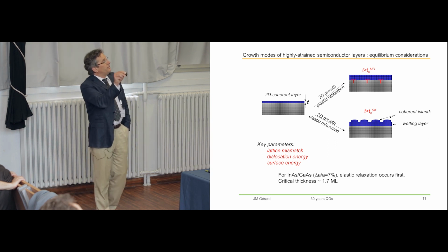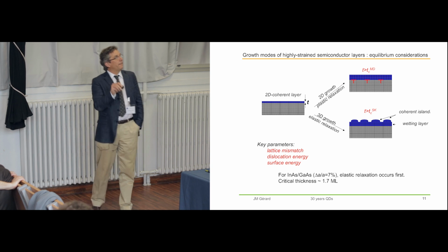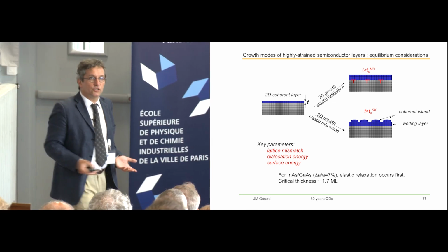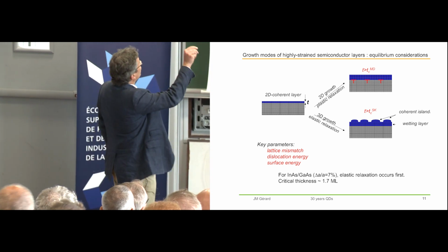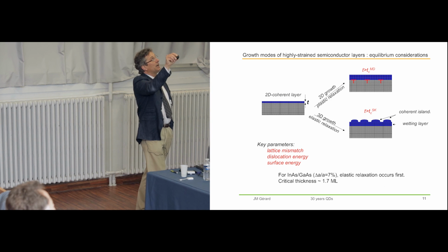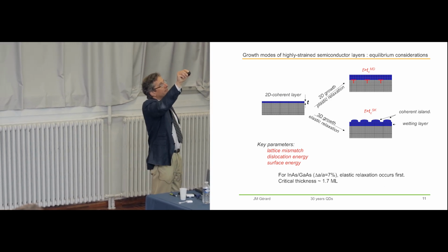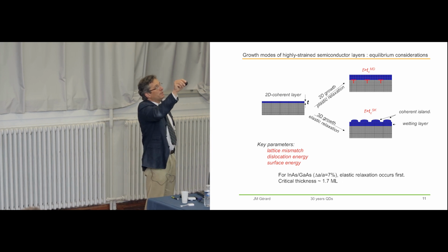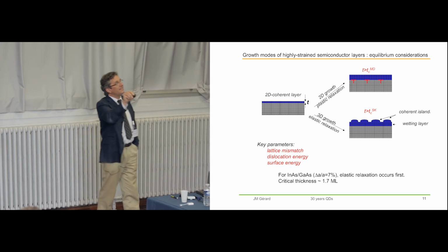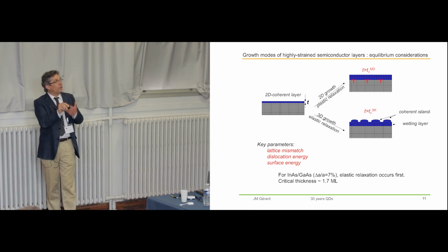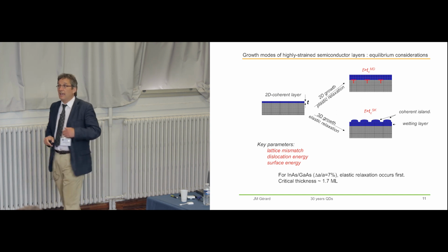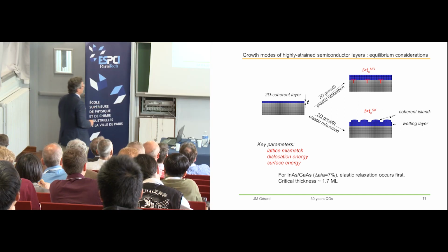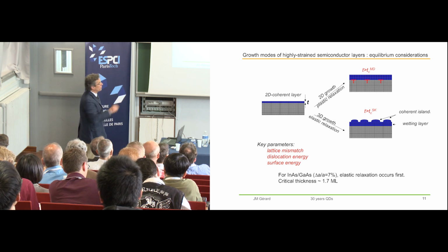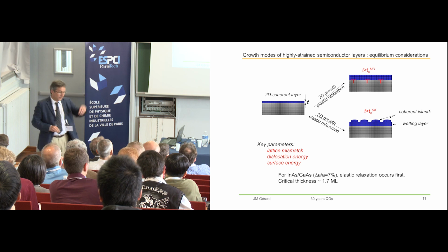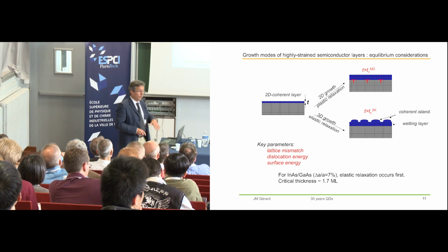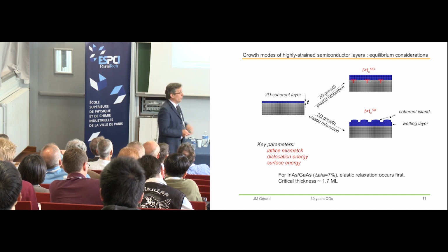We know that when we deposit a strained layer on top of a substrate, there are two possible relaxation paths. First of all, you have a coherent growth with no relaxation. But after that, you can either put dislocations on the interface here, or you can build islands on the surface. This is elastic relaxation. And in fact, when you have a lot of strain, such as is the case for indium arsenide on gallium arsenide, elastic relaxation occurs first. So what Goldstein had seen was the formation of these tiny islands on top of the surface. After that, he deposited again gallium arsenide on top, and then the surface flattens, and you get a two-dimensional layer again.